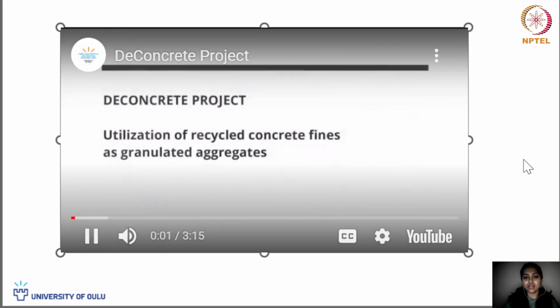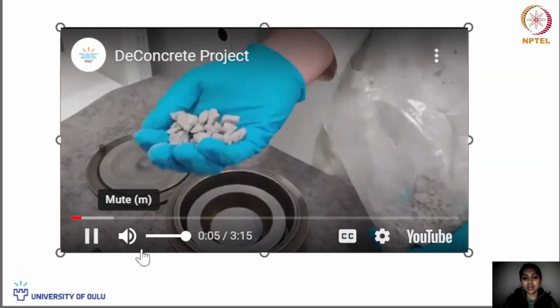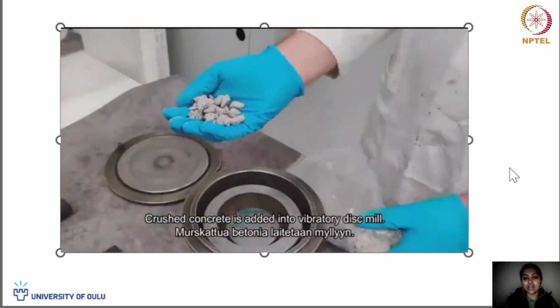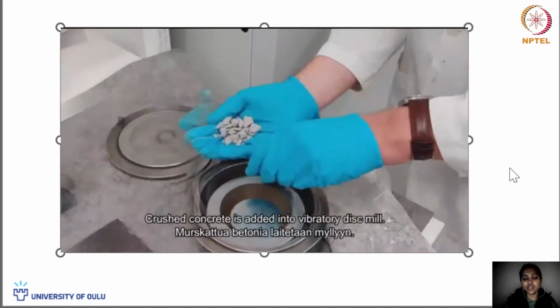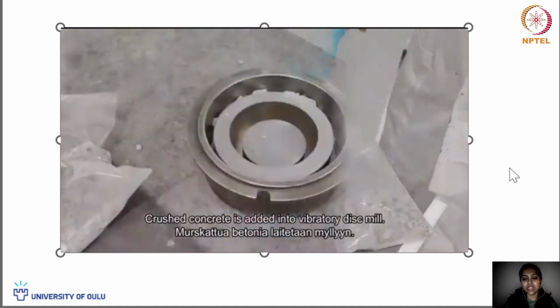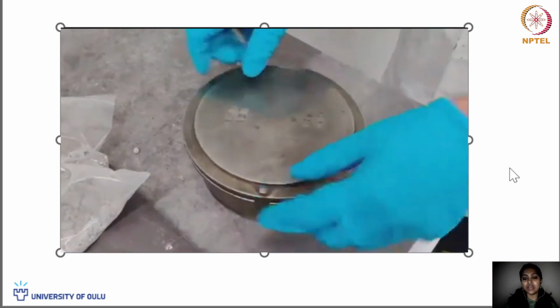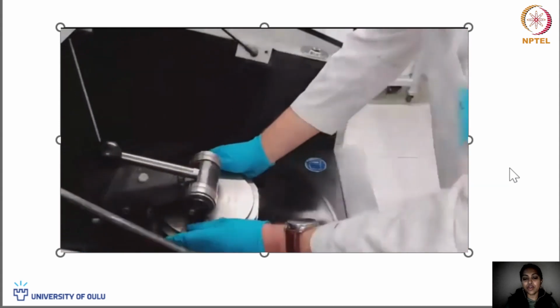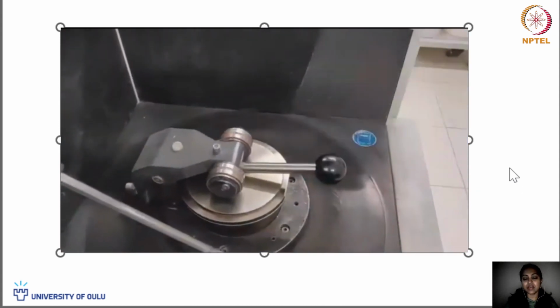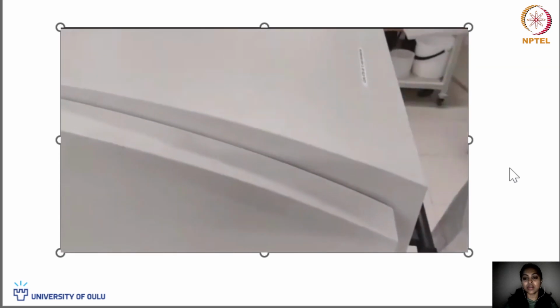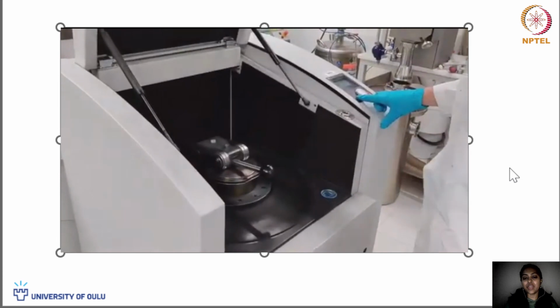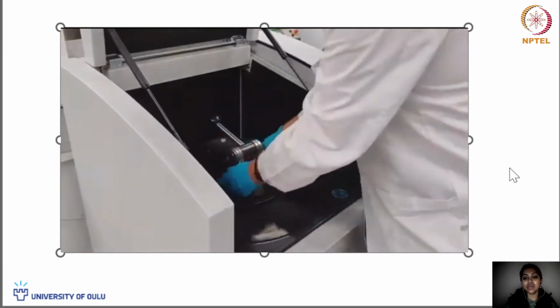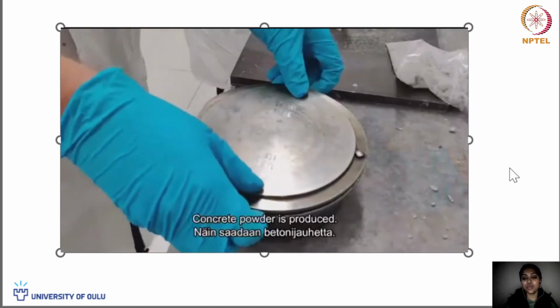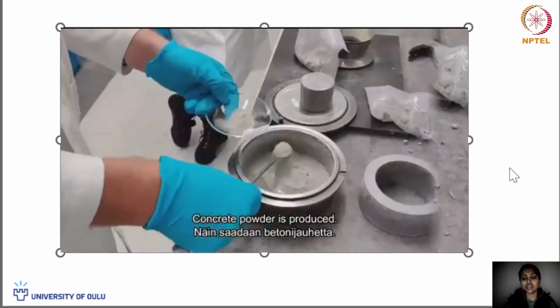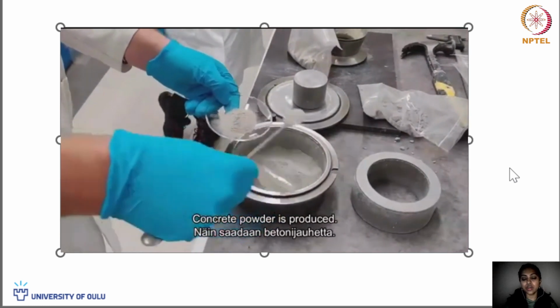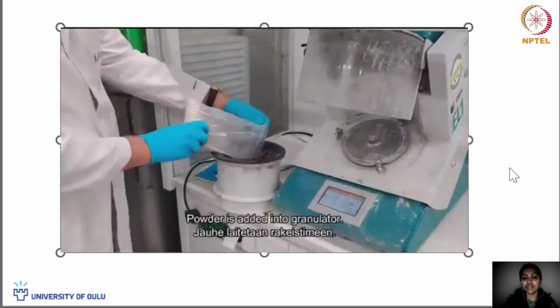Before going to the actual results, let's see what has been done in this project. What we did is we used this recycled concrete material and milled it into a finer fraction to simulate the property of the fines from the crusher or the recycled concrete production. We also crushed all the fractions including both the cement and the mortar, assuming a low quality fine that also crushes the aggregate together. So we didn't do a careful separation of the aggregate from the fines.